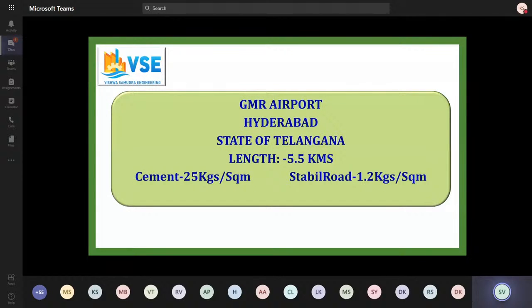We finished around 80,000. The balance is on the main runway, which will be starting by December 1st. The cement we used is around 25 kgs per square meter, and Stable Road was around 1.2 kgs. This is because there was already a lot of aggregate at the bottom, so the surface was relatively strong. So we used a smaller amount of Stable Road.